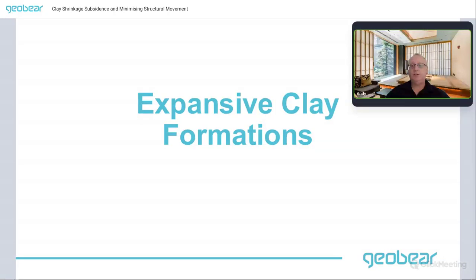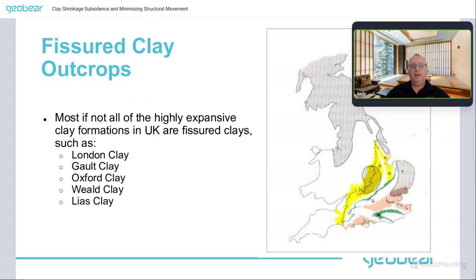Expansive clay formations. So most, if not all, of the highly expansive clay formations in the UK are fissured clays. So these are clays that will be deemed to be high volume change potential. I will caveat and say that most clay formations have the potential to cause shrink swell problems. Even low plasticity glacial till and other formations like that, alluvial clays can show shrink swell behavior.